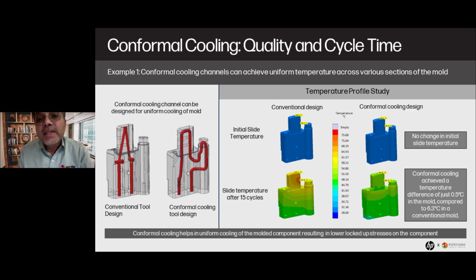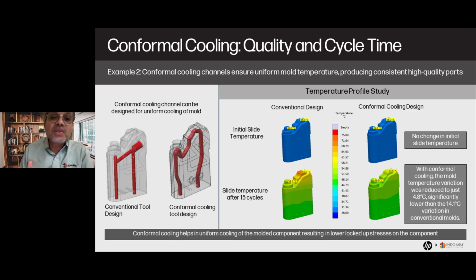Now, the initial temperature was, of course, before we started molding, obviously all of the mold elements were at a similar temperature. But when we run 15, 20, 30 cycles, for lack of appropriate cooling, certain elements on the tool become significantly hotter than the other elements, and that actually caused a lot of quality issues in the process. By adopting the conformal cooling tool design, if you see here on your right side, the temperature difference between the various tool elements dropped to only 0.5 degrees Celsius compared to 6.3 degrees Celsius on a conventional mold. That was a huge advantage for us, and we were not able to achieve that with the conventional tool design and conventional tool manufacturing.